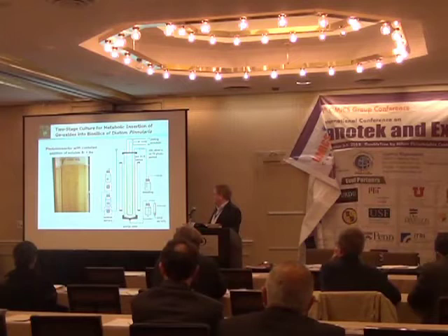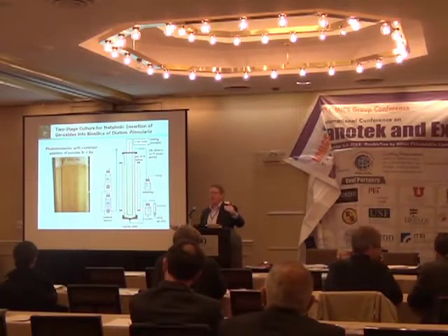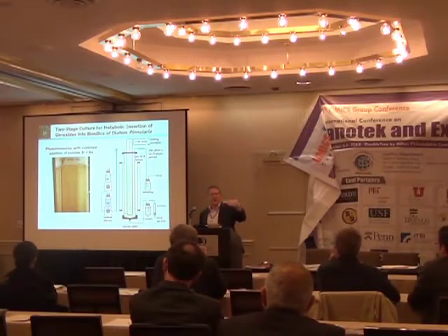We use an externally illuminated bioreactor to cultivate these organisms because their photosynthesis requires light as an energy source and carbon dioxide as a carbon source. But since they have inorganic-based shells, we also do a programmed feeding of dissolved silicon and dissolved germanium, and these organisms take up these precursors in the soluble state and then fabricate nanostructured materials from them.